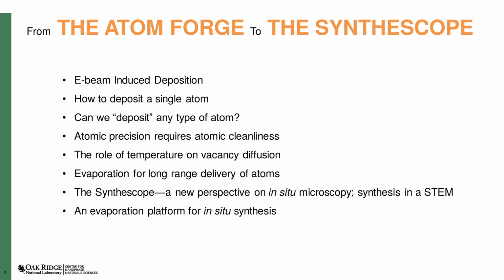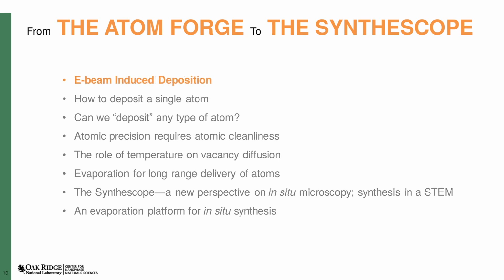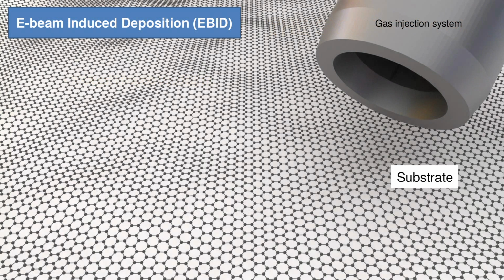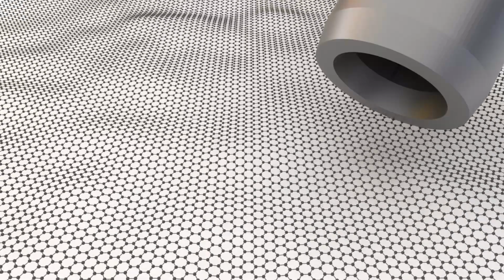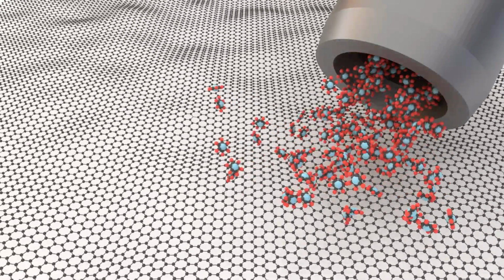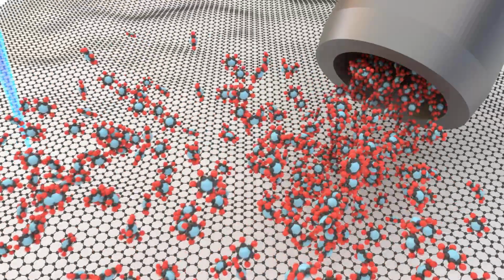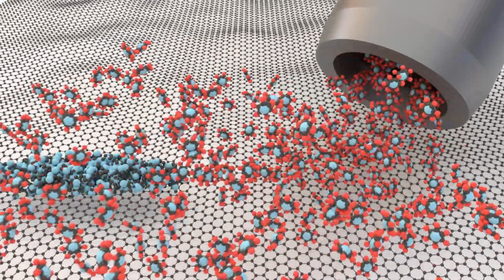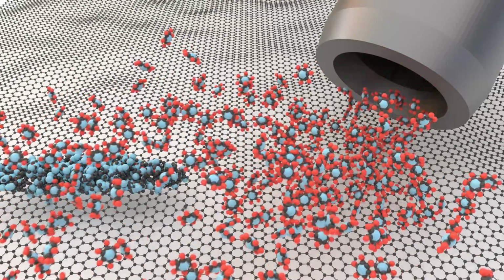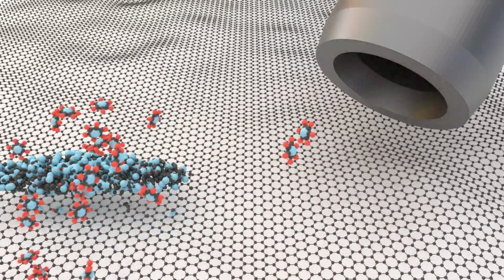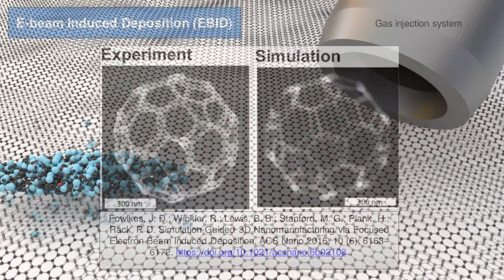Can we think about performing synthesis at the scale of a single atom? What would this mean? We begin by looking at e-beam-induced deposition. This is a well-known top-down approach to locally depositing material on a substrate using an e-beam. The substrate shown here is graphene. We then use a gas injection system to flow a molecular precursor gas across the substrate. We then irradiate some area with the e-beam and move it where we want to deposit material. The e-beam dissociates the precursor gas, which becomes chemically reactive and then bonds to the substrate, forming a deposit site.